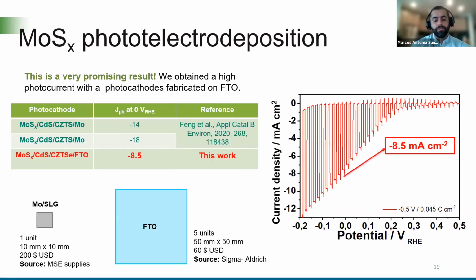Although the photocurrents reported in the literature for the copper zinc tin sulfoselenide photocathodes containing molybdenum sulfide as a co-catalyst are higher than the ones that we reached, our results are very promising because we fabricated our photocathodes using an inexpensive substrate in comparison with the molybdenum soda-lime glass.